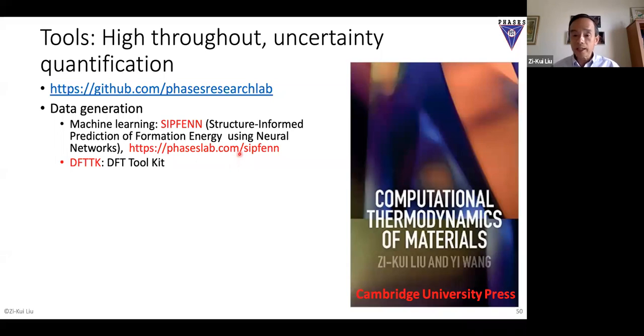For example, if you get a compound, I don't know, an oxide, and you need the formation energy, take this code, put your structure into it, and it will predict the formation energy for you at 0 Kelvin. Basically it gives you delta H. Delta H doesn't change with the temperature much, okay? So it gives you delta H, so to speak.